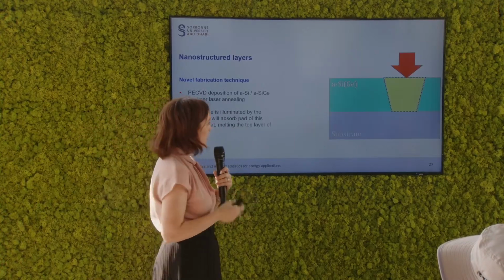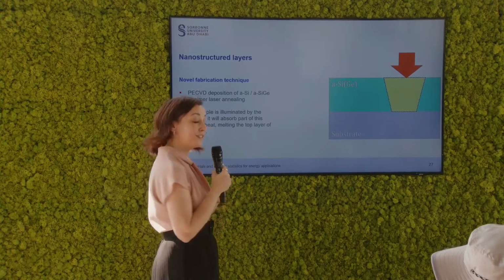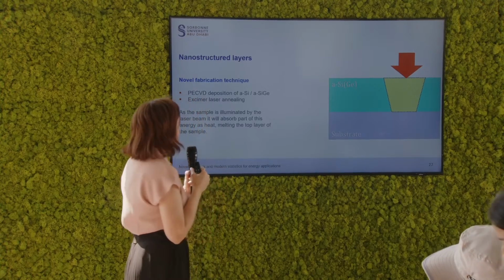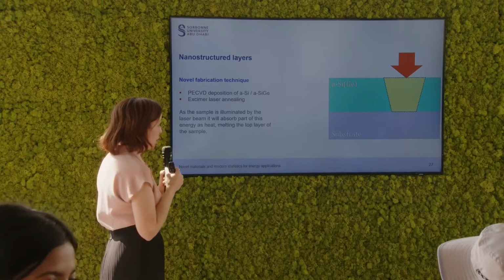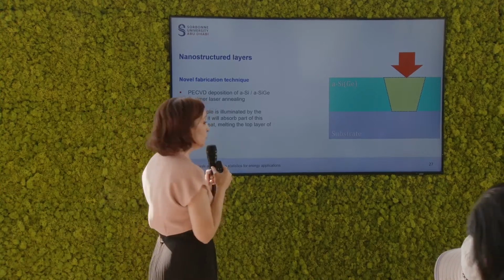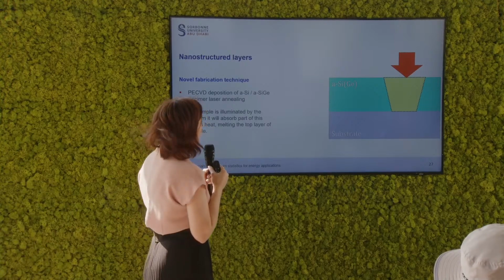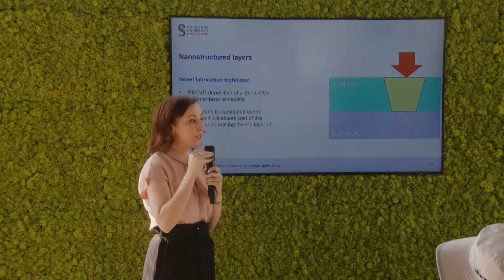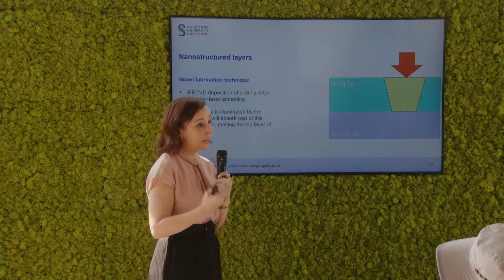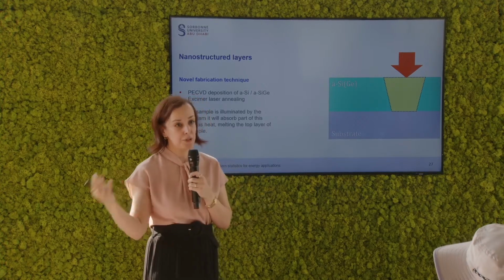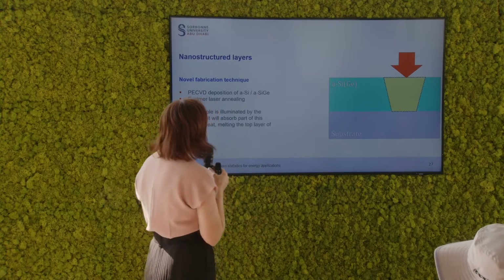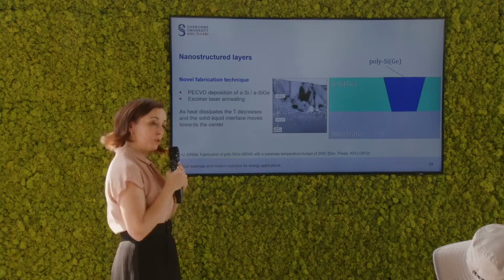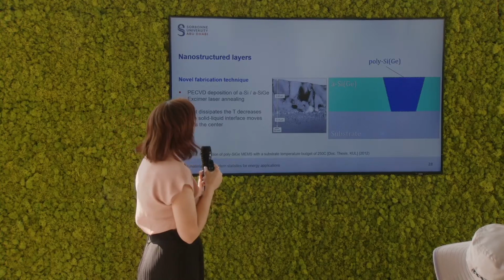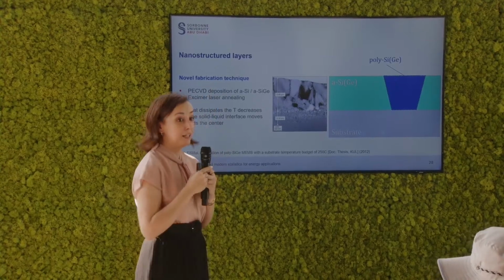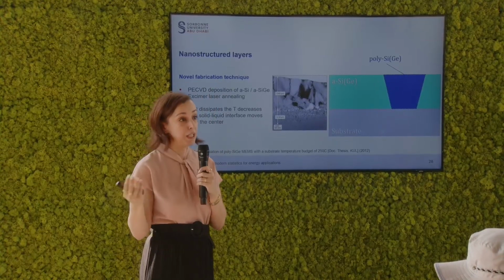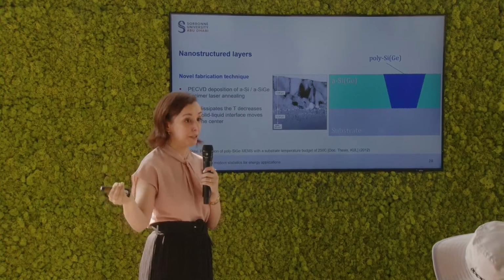What happens, though, as the laser shines onto your amorphous silicon or silicon germanium sample is that it will absorb part of that light or that energy as heat. It will create a solid-liquid interface, and that interface or that top layer will propagate into the depth of the material. How far it propagates downwards depends on your laser energy. The higher the laser energy, the more the melt depth is going to be. And then the sample cools down and the heat dissipates, and the solid-liquid interface will move to the center and then back at the very top. And what you're left with is a polycrystalline material. So at this point, your material can actually conduct electricity if need be.